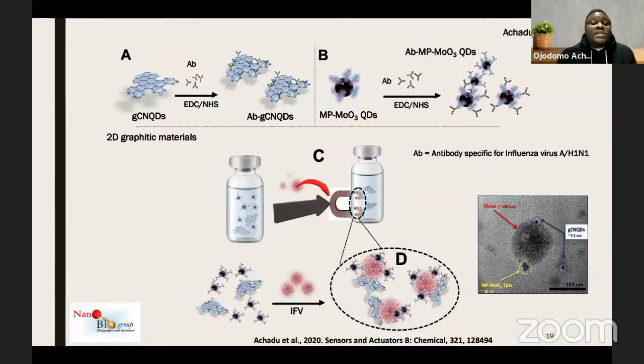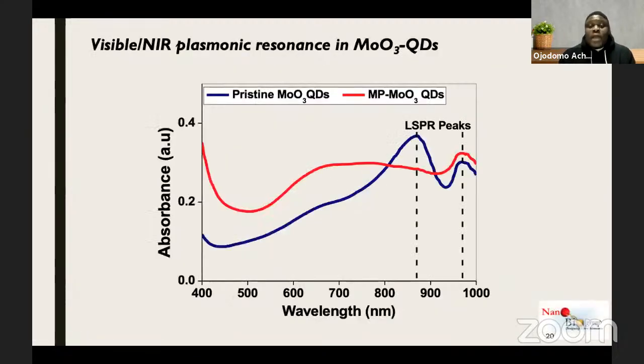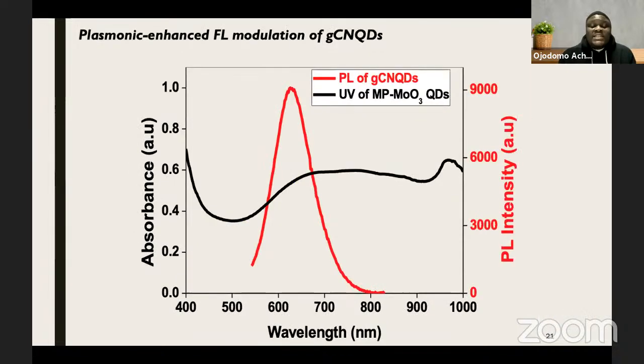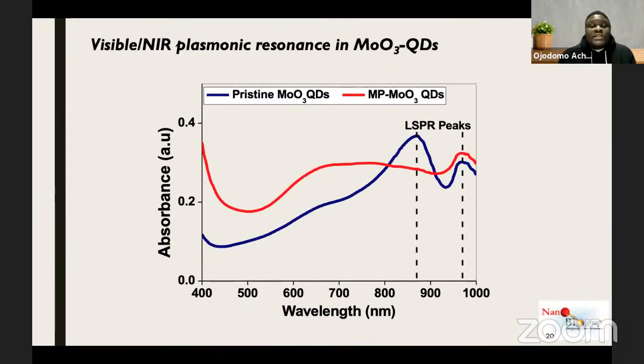And what we simply did, in this case, not SERS, we actually used fluorescence spectroscopy for the detection here. We conjugated antibody for influenza A virus, H1N1, that can also recognize H3N2. We conjugated them to the graphitic carbon nitride and also the molybdenum trioxide quantum dots. So we form a sandwich immunocomplex by interacting them in the presence of the influenza virus. By this sandwich immunocomplexing, we're able to induce some kind of localized plasmonic coupling to significantly enhance the fluorescence of the graphitic carbon nitride QD.